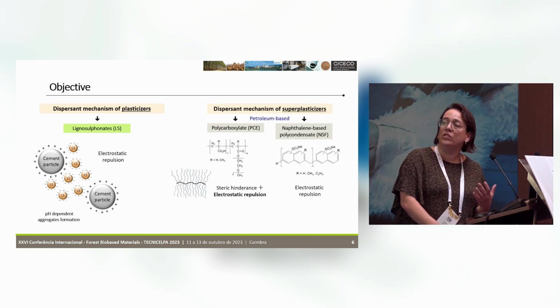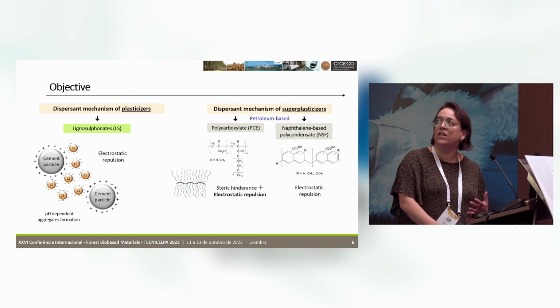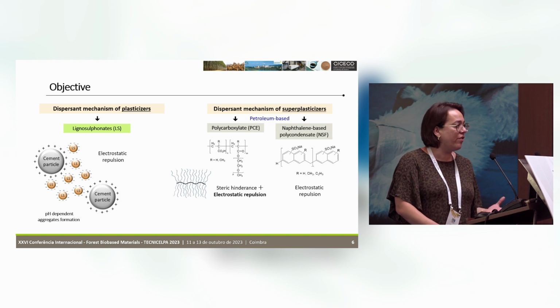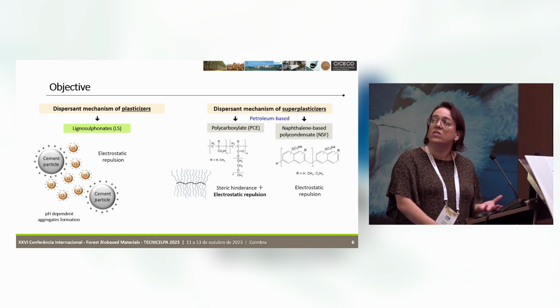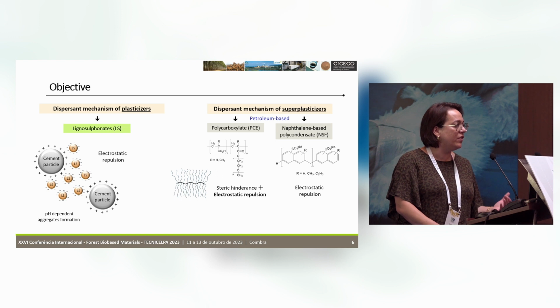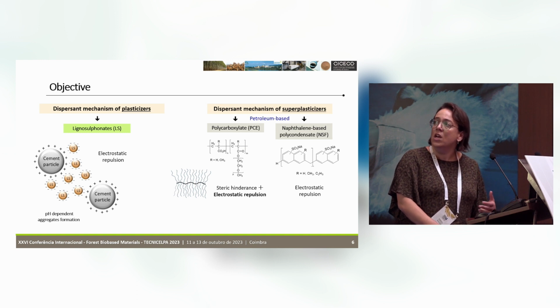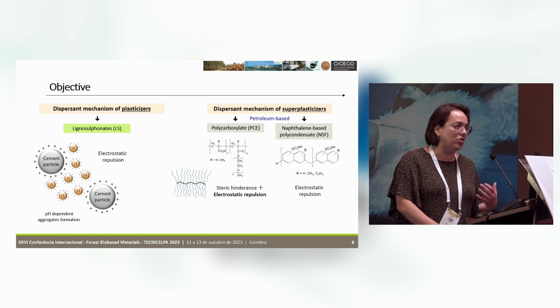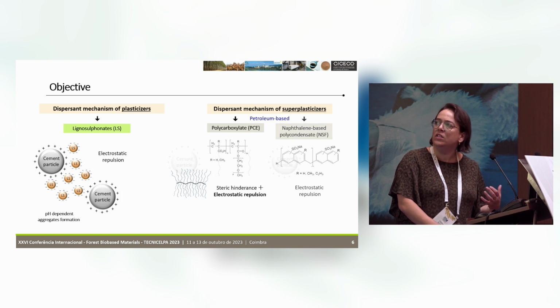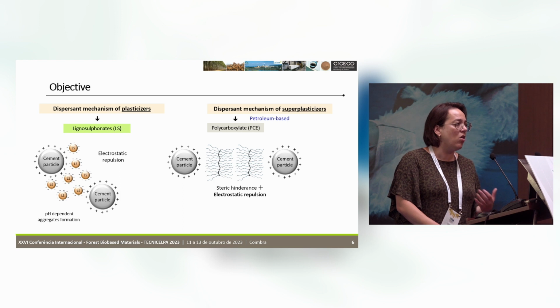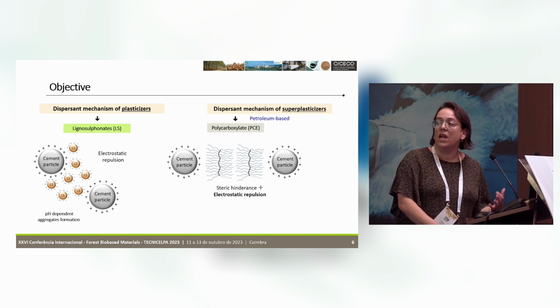You have here two examples, polycarboxylates and naphthalene-based polycondensates. Both of them are petroleum-based products. In the industry, they are used mixed with lignosulfonates because lignosulfonates are not enough to provide the dispersant efficiency required for the product. The dispersion mechanism of these products is also based on electrostatic repulsion forces, but in the case of polycarboxylates, it also combines steric hindrance.